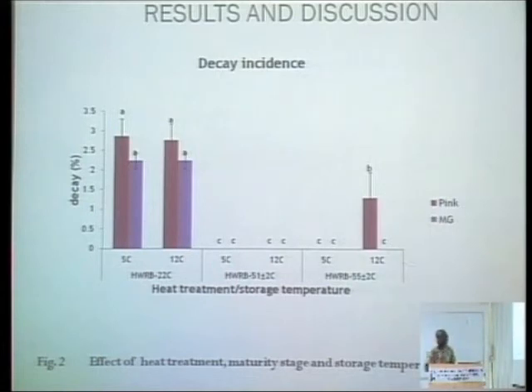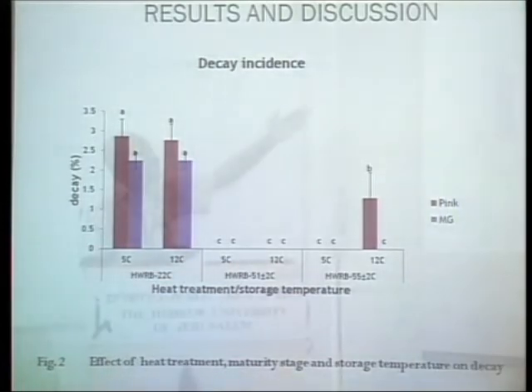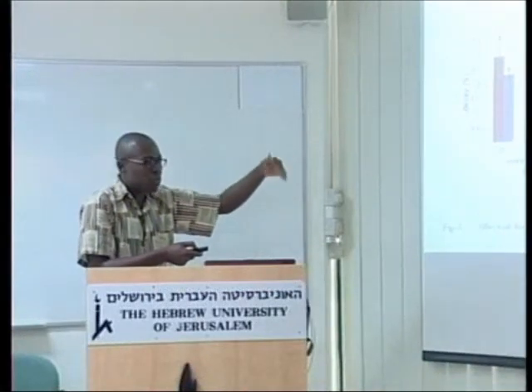So the idea, we washed this fruit at 51 and at 55. That's where we washed it. But in my materials and methods, I mentioned that Fallik et al. also did a similar experiment, but it wasn't at 51. It was at 52. So 51 plus or minus 2 will be able to inhibit decay and chilling injury. But something above 55, of course, can inhibit chilling injury, but it can cause decay due to heat damage.